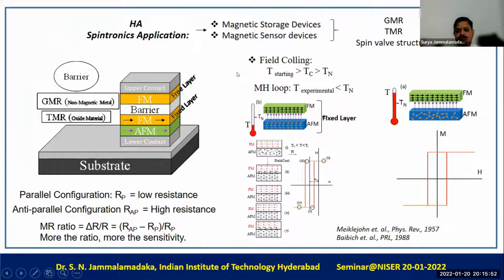Another important concept that I would like to discuss here is the exchange bias phenomenon. Exchange bias is basically an interfacial phenomenon. This can be achieved by cooling the ferromagnetic-antiferromagnetic interface through the Néel temperature of the antiferromagnetic material through a field cooling process. For instance, in diagram A, initially one has to make sure that the temperature of the system is above the Néel temperature and below the Curie temperature of the material, so that the spins in the antiferromagnetic material will be randomly oriented, and the spins in the ferromagnetic material are oriented in one direction.